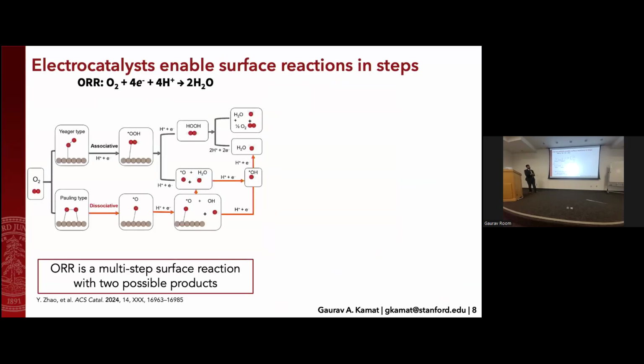Taking that oxygen reduction reaction from before, you start with molecular oxygen and it will stick to your surface. Depending on how it sticks, it may want to stay as O2, or that oxygen-oxygen bond may break. And you have this whole cascading set of steps that all have different energies. And you can end at either hydrogen peroxide as a product, or you can end at water as a product.